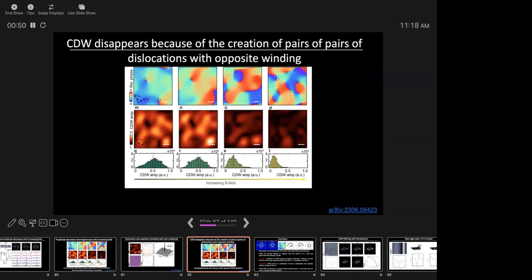Perhaps you would see a similar field dependence if the CDW wasn't the daughter of the pair density wave, but coupled to a spin density wave. Because there was also this funny feature in the susceptibilities, right? Yeah. But nobody's found a spin density wave. That doesn't mean it doesn't exist. If the CDW is so weak, then the SDW could also be extremely weak. It's possible, although I don't understand why it would be sensitive to HC2. Because we have data in 2 different directions and it goes like HC2.